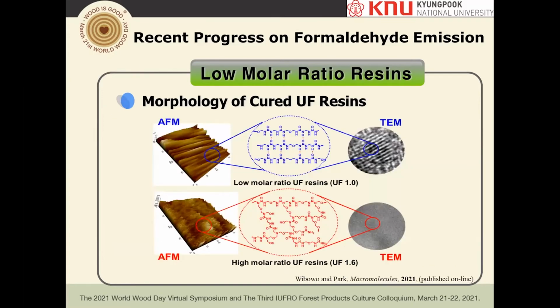And recently we did the AFM and the TEM to look at the morphology of the cured resin. As you see here, on the right-hand side, AFM shows pretty much the lamellar crystal structure for the low molar ratio resins. We also confirmed the lamellar structure with the TEM. However, the high molar ratio resins are pretty much amorphous, as shown by AFM and TEM. So that means the low molar ratio has crystal structures of lamellar type.